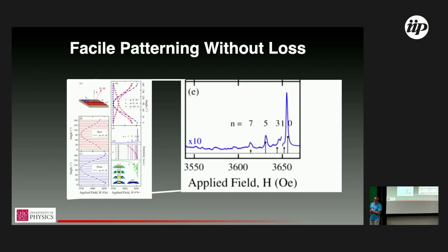I'm sorry if you mentioned this already in your previous talk, but why is it that you only have the odd modes here? Are those the only ones that are visible in your measurement? It's a cavity measurement, and so you need the odd parity to couple to the EM field. Okay, thanks. In principle, I actually do think we're seeing the even modes, because experiments are never as symmetry preserving as the underlying theory, but the calculations are more straightforward, certainly for the mu-max. So we're just doing the quantitative comparison there.